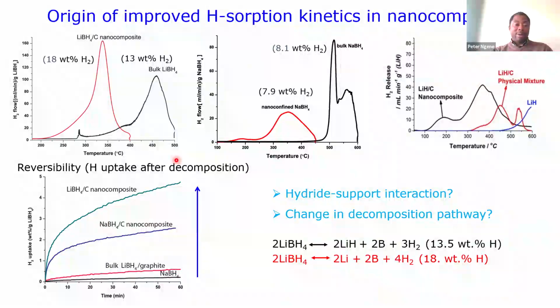And of course, NMR. We did a lot of NMR work, but with NMR you cannot really do in-situ measurements to look at the phases you are forming during the decomposition of this material. So that is why we looked at which other technique we could use. And because these materials are very light, it was difficult to use even soft X-rays to do this.